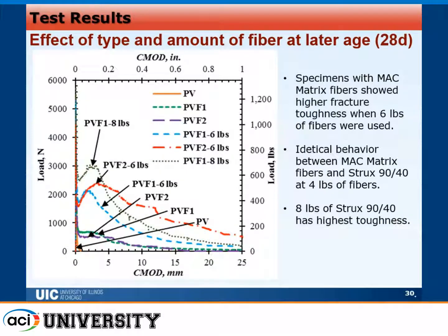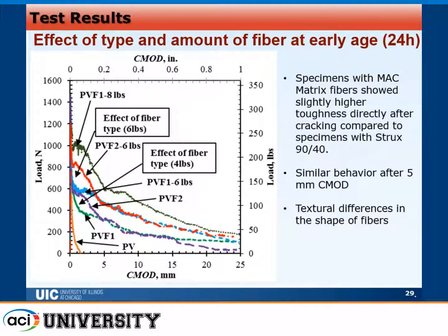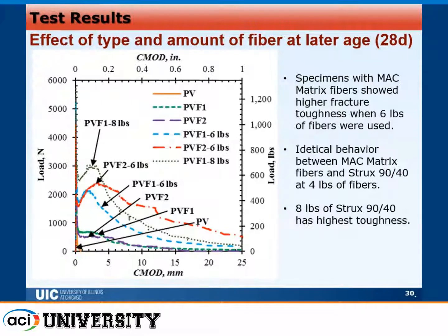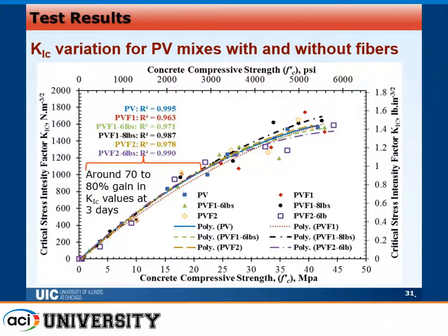Similar observation here at a later age. This one was at 24 hours, as you can see in here. Almost the same observation at 28 days. Always the 8 pounds was outperforming all of them.